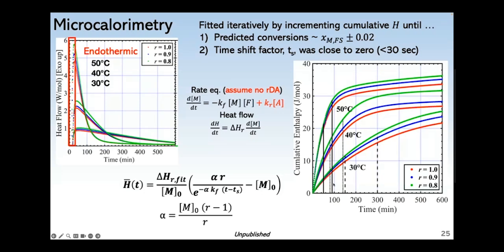So to figure out how much I need to shift these up, I incremented the cumulative enthalpy very gradually until the predicted conversion at the gel time was close to the Flory-Stockmayer conversion. And then the other stopping criterion was that the time shift factor became close to zero. Once both of those criteria were met, I used the last iteration of the fitting equation to predict the early heat flow, which shows you the fully corrected plot here.